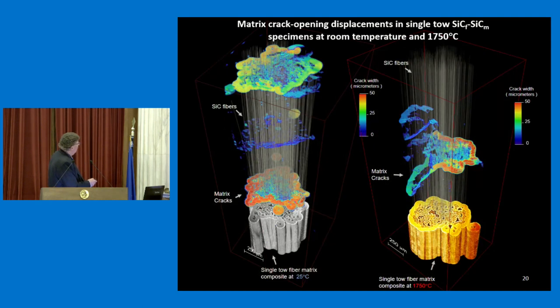But we can get lots of information. This is slightly different imaging, same materials, same samples we looked at. You can see the fibers here. We're not looking at pullout now, but these colored regions represent the cracks. And the color here represents the width of the crack, what's called the opening displacement. And that can be used to measure the toughness in these regions.